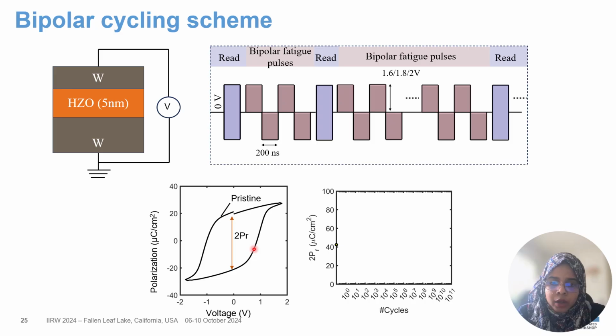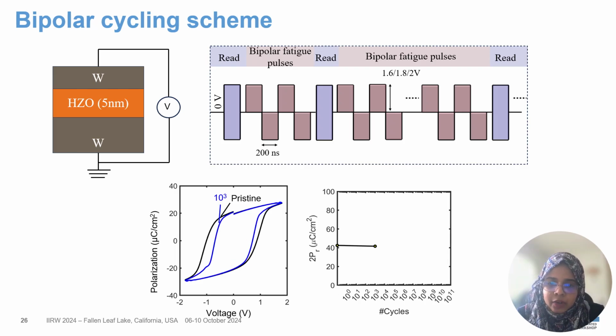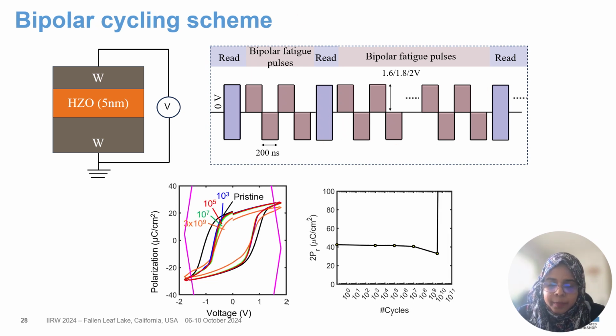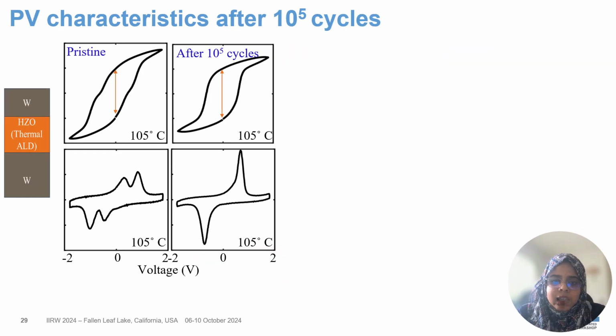So for waking up and for also endurance measurement, what we do is we measure the PV loop at pristine state, and then we keep cycling and measure the PV after different amounts of cycles until the samples break. The cycles that our devices can endure before breakdown, we call the endurance of our device. Now let's see how many cycles are needed for thermal ALD for waking it up.